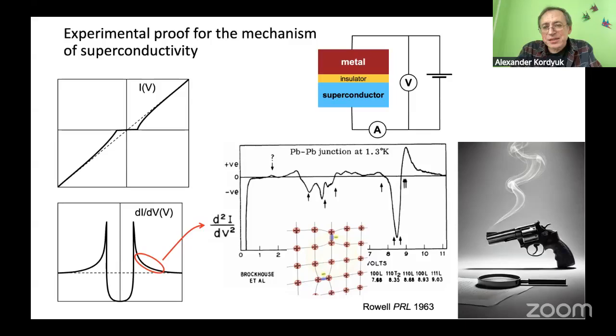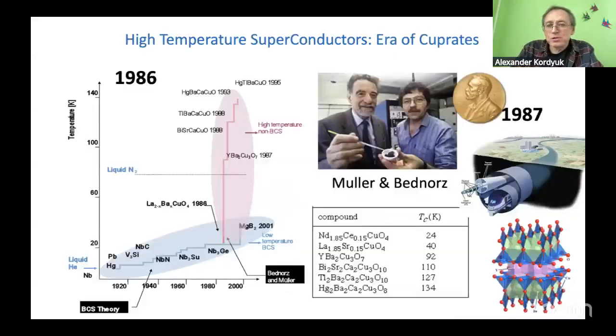At that time it was shown that these peaks here are identical to the energy positions of the optical phonon modes. Therefore this interaction was caused by the phonon spectrum. Therefore, it was evidence that it is phonons, that Bardeen-Cooper-Schrieffer are correct, that it is phonons which are the glue to explain this superconductivity.